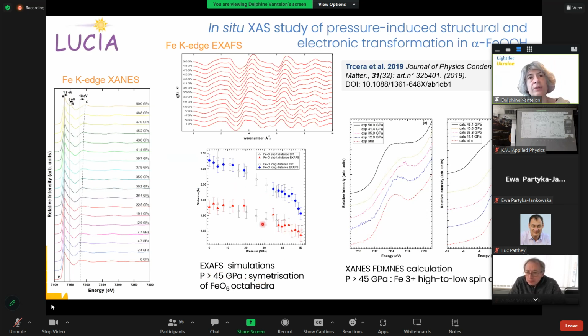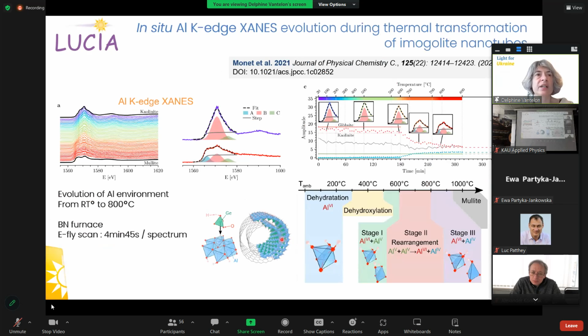of the iron octahedra. And with the XANES and the FDMNES calculation, they could observe a high to low spin crossover of the iron 3+, also above 45 gigapascal. Now I switch to the modification under temperature, here of nanotubes of imogolite. And so we use a furnace up to 800 degrees Celsius.